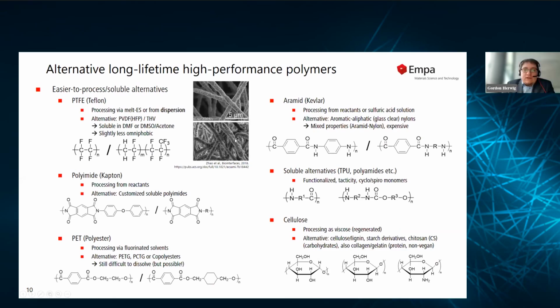Yeah, then you have to adjust the temperature, and you're using a sacrificial polymer on the outside. In this case, they often use PEO or PVA, which simply gets burned off. So while it's burning off, it's still providing some sort of structure, some sort of integrity, like a scaffold around it. And that's why this looks like this after heat treatment. So this is roughly 350 degrees, just above the melting temperature of PTFE. And there's loads of studies on which temperature exactly to use. What we are working on is a polymer that actually melts higher than this. And then you have the option to theoretically form very nice smooth structures, but it's not as simple at the moment.